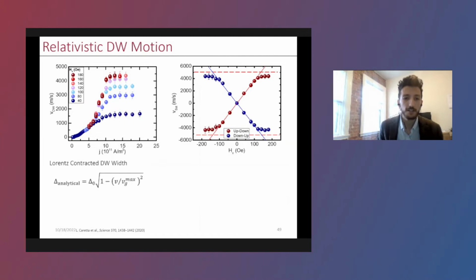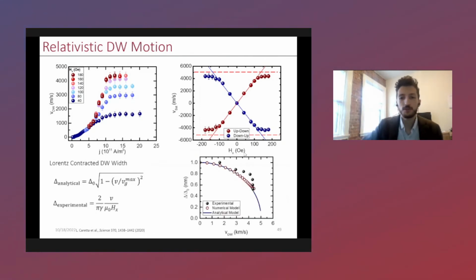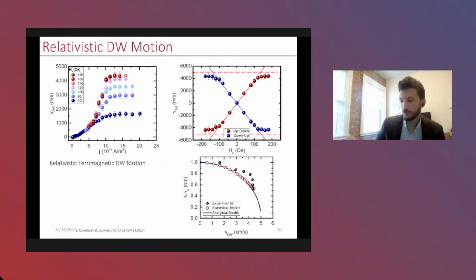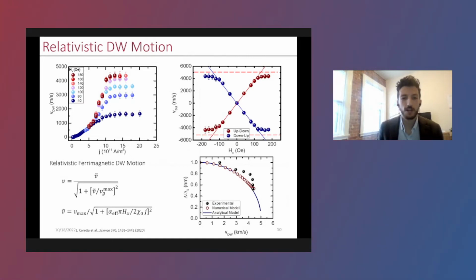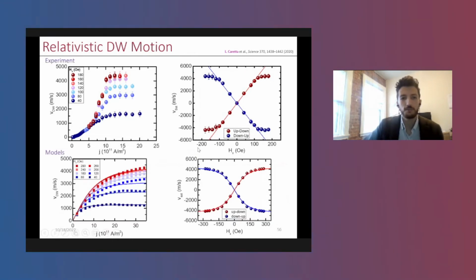Which means that essentially we have to take into account the Lorentz contraction of the domain wall as it's traveling this fast. And so we can analytically and numerically compute what this domain wall Lorentz contraction would be as a function of speed, and even experimentally infer what the Lorentz contraction of the domain wall is from this data, and find that these match quite closely. So we've adapted the ferromagnetic domain wall motion equations that I showed you earlier, this 1D model, to account for this Lorentz domain wall contraction. And we can do this analytically with these equations, and also using numerical simulations. And what we find is that these models, both qualitatively and quantitatively, match the experimental data quite well.